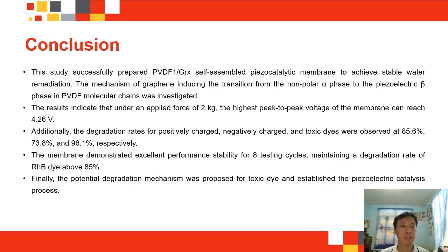Now for the conclusion. This study successfully prepared PVDF1 graphene X self-assembling piezocatalytic membrane to achieve stable water remediation. The mechanism of graphene inducing the transition from the nonpolar alpha phase to the piezoelectric beta phase in PVDF molecular chains was investigated. Next, the results indicate that under an applied force of 2 kilograms, the highest peak-to-peak voltage of the membrane can reach 4.26 volts. Additionally, the degradation rates for positively charged, negatively charged, and toxic dyes were observed at 85.6%, 73.8%, and 96.1% respectively. Also, the membrane demonstrated excellent performance stability for 8 testing cycles, maintaining a degradation rate of RHB dye above 85%. Finally, the potential degradation mechanism was proposed for toxic dye and established the piezoelectric catalysis process.